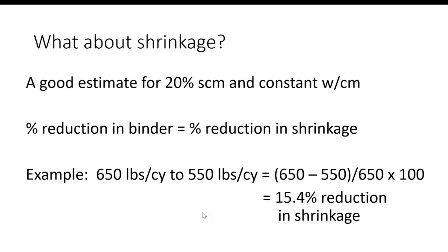I mean, you can do it with silica fume as well. If I was going to do it with silica fume, I would still be at 600 pounds of total cementitious. Instead of using 20% fly ash, I would just use the 5% silica fume replacement. And I would probably just need to up my admixture dosage to make that work. Did that help?